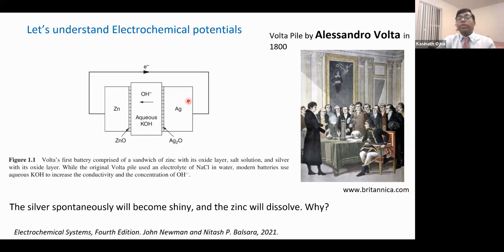Now, if you make the sandwich and then connect one electrode to the other, electron flow happens. With time, you see that the silver side, with silver oxide, is black, and then the silver side becomes shiny, while the zinc is dissolving into the electrolyte. That happens because of the electrochemical potential of the two species. Silver oxide, basically silver plus, is getting reduced and forming silver metal, which is shiny, metallic silver, while zinc is getting oxidized and becomes zinc ions, and that goes into the electrolyte. So zinc is dissolving while silver becomes shiny. That all depends on the electrochemical potential of the two species.